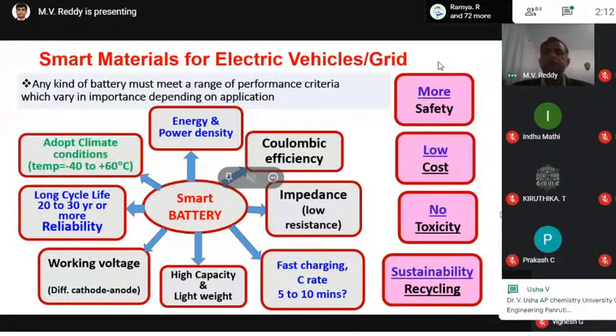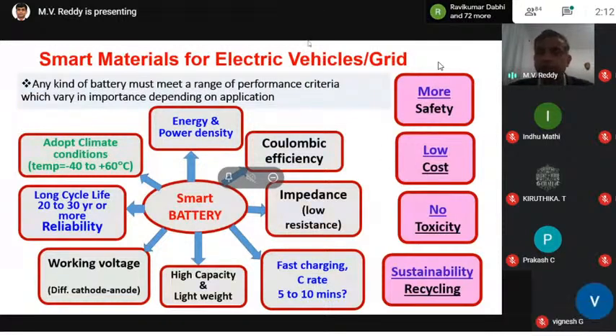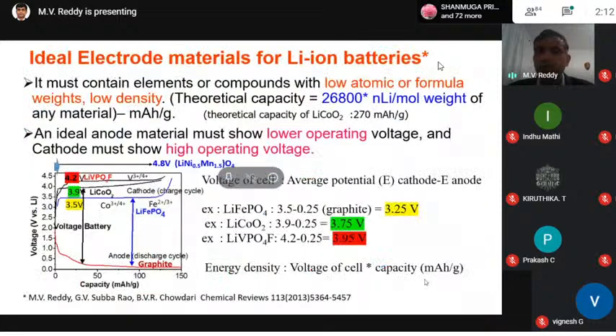Diffusion of the lithium ions is a little bit difficult with fast charging. That's why, at the end, if you solve all these problems, you have to look for safer material, low cost, and low toxicity. And at the end, you have to consider sustainable recycling. It's very important. If you use too much material, you have to recover materials. So always look for low atomic weight, so then only we can get higher theoretical capacity.